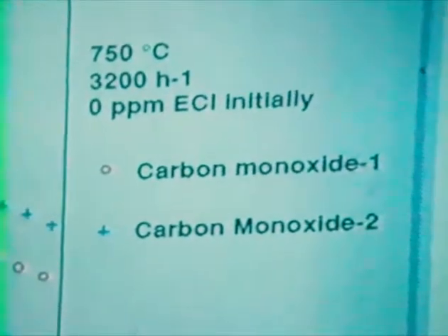Harold was concerned with butane oxidation, and he wanted to know whether or not he was releasing butane radicals from the catalyst surface. So what he did was, he made a catalyst bed, put a void space before and after the catalyst bed, with the reasoning that if you had a homogeneous component to the reaction, and you ran two reactions simultaneously, the one with the void space after the catalyst bed would show enhanced rates to products created in the gas phase if you kicked radicals into the gas phase. So we used his technique here. Reactor number 2 is the one with the void space after the catalyst. Reactor number 1 is the void space before.